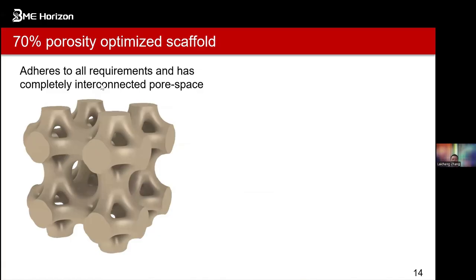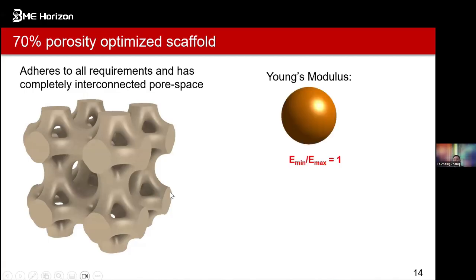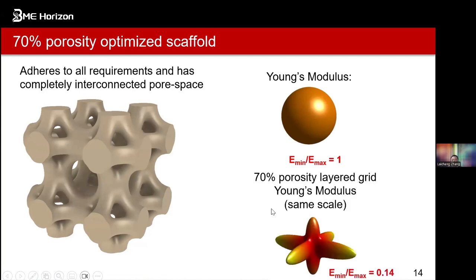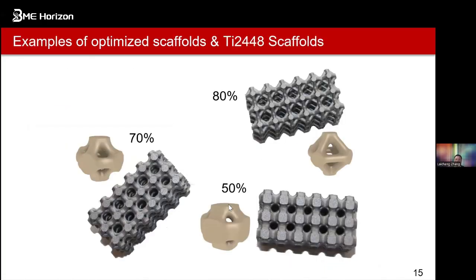For this kind of criteria, we designed several types of porosity-optimized scaffolds. For example, we adhere to all the requirements and we have a completely interconnected pore space. This is complicated, but the Young's modulus is homogeneous in all directions. Compared for the 70% porosity scaffold, it's roughly 0.14. So that means the structures are homogeneous in this way. This is the unit cell we developed. You see we can go from 10, 20, 30, 40, 50, 55, 60, 65, roughly up to 90% porosity.